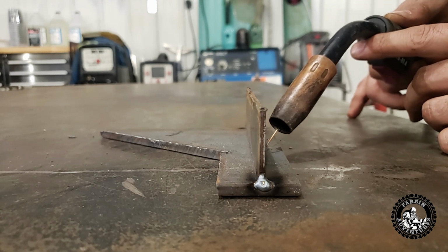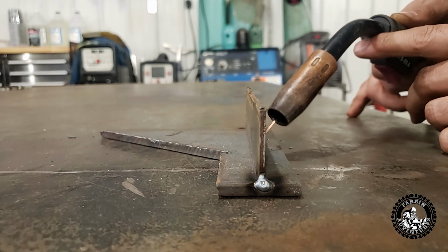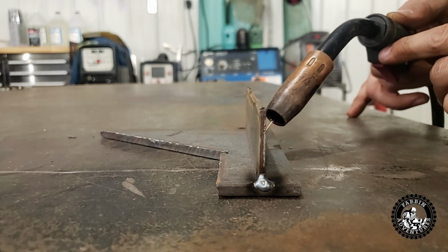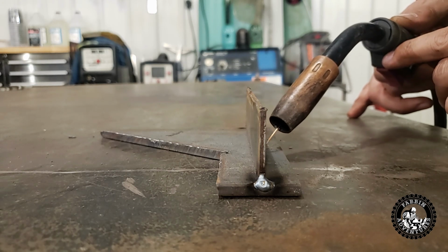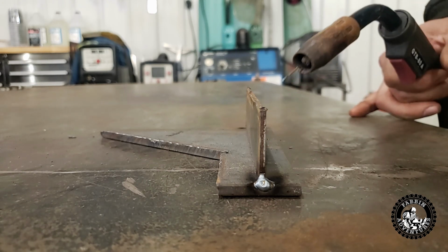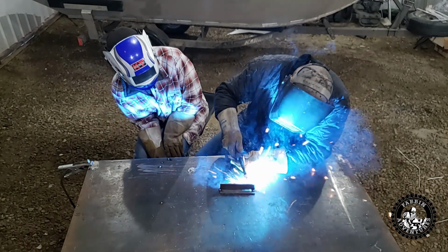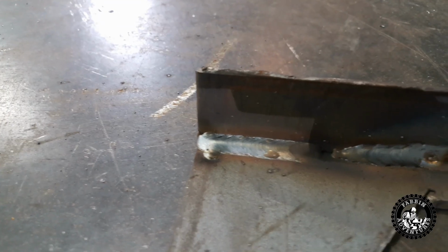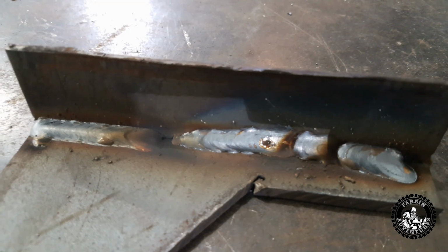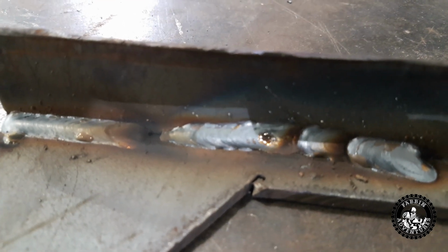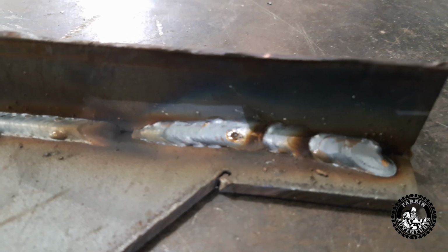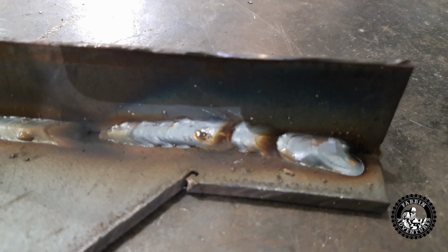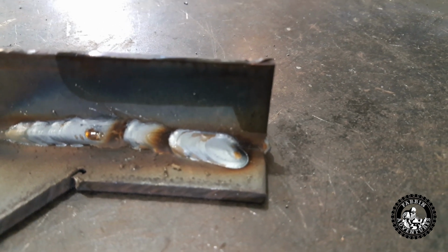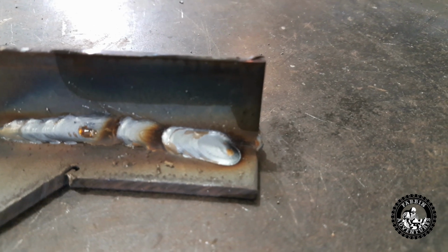When you finish off your weld, I typically like to do a circle, 1 or 2 circles, and then stop the weld, and it'll be a nice finished weld instead of kind of a long, elongated, drawn out bead. All right, so there's my weld, 1/4 inch to 1/8 inch. And then there's Crystal. You can see evidence of cold lap there, quite a bit of cold lap. She wasn't holding enough heat on the 1/4 inch plate, putting the wire too much into the corner. Lots of cold lap. And then the last one, where she pointed the gun more straight down into the 1/4 inch plate, is way better.